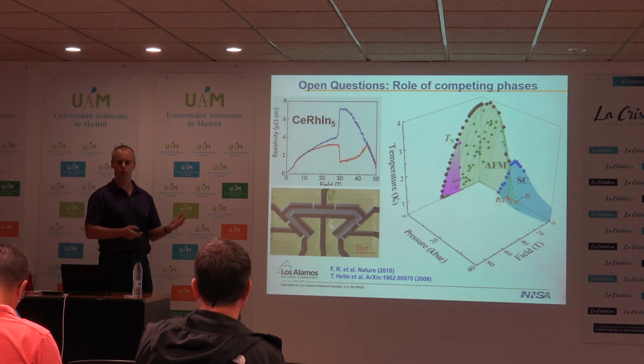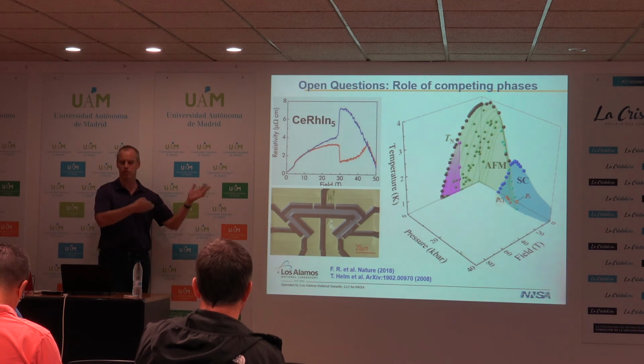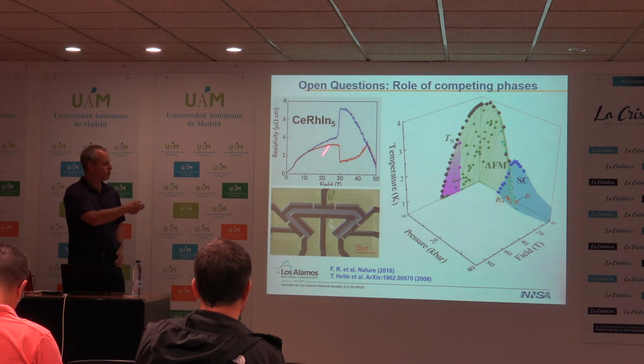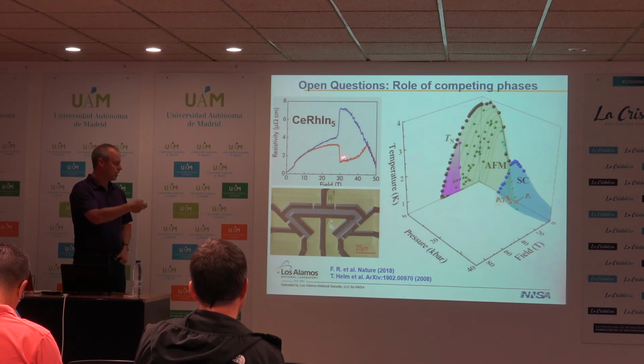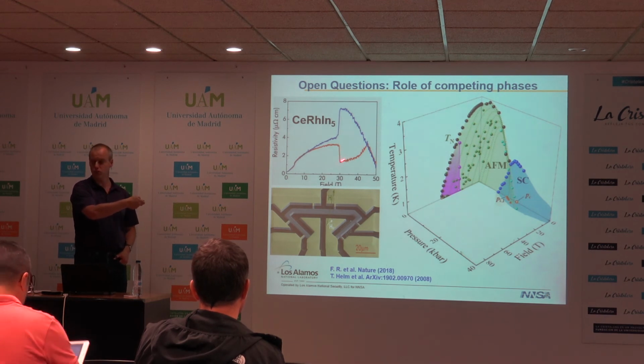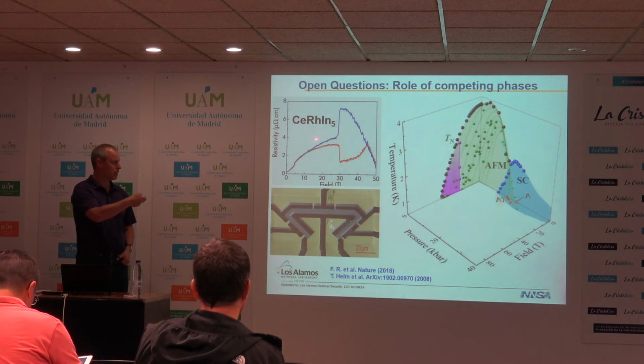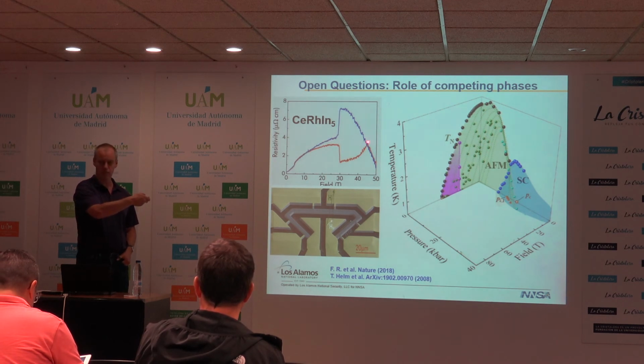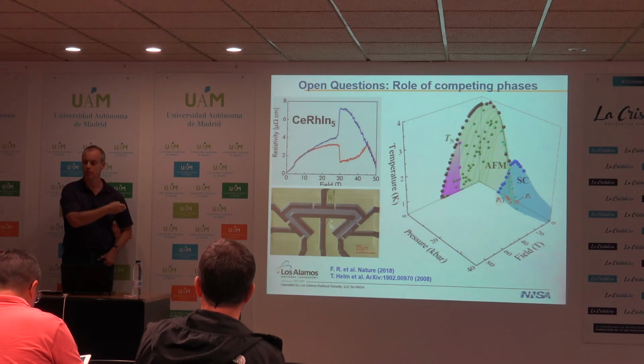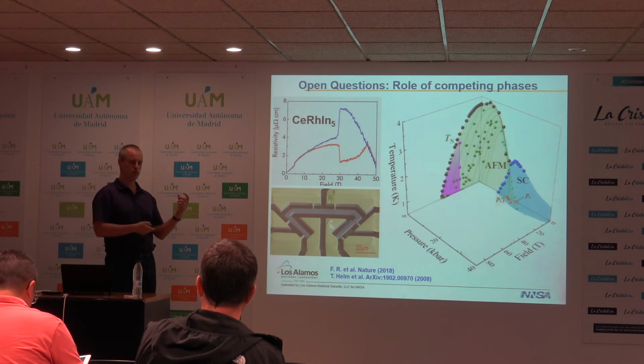And the first thing you would say is, oh, well, you must have some sort of magnetic structural change there that is causing this. It's 30 Tesla, so it's very hard to do neutrons. But NMR has been done. There seems to be no change in the magnetic structure as you cross here. Magnetic susceptibility, torque magnetometry has been done. There's really no change in the magnetic structure from the magnetic susceptibility. Magnetostriction has been done. There's a small anomaly in the magnetostriction, but it's so small that it doesn't seem like that is what could be driving the transition.